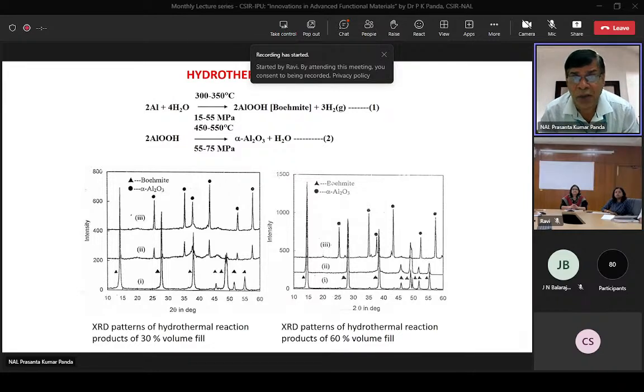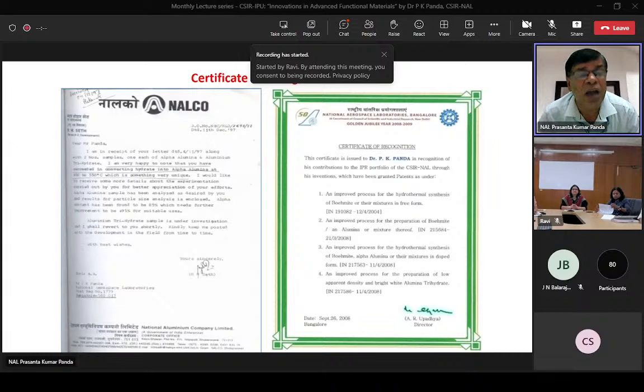I collected some samples from NALCO and we tried their alumina trihydrate, which is prepared out of bauxite to make it much cheaper, and that also worked. After that, we communicated to NALCO, and at that time the DGM mentioned, I am very happy to note that you have succeeded in converting hydrate into alpha alumina at 450 to 500 degrees centigrade, which is something very unique. But after that, the person I think got transferred, and we were not able to have continuity in the technology transfer. But this technology, I still feel it is very interesting.